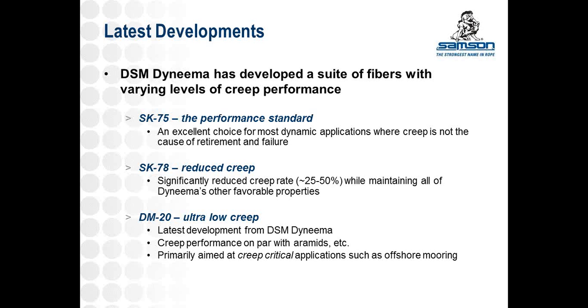Finally, DSM Dyneema has just released a brand new fiber, which they call DM20, which is their ultra-low creep fiber. Now this is a complete change. They actually went ahead and changed some of the chemistry in the fiber as well as the production process, and this has led to creep performance on par with fibers such as the aramids. So it is going to have a negligible amount of creep strain over its lifetime. That doesn't mean it won't have a creep failure. It will. It'll last much, much longer than SK75 or SK78, and it won't be stretching in that time. But like I said, it will happen to everything. So far, this fiber is brand new. It's primarily being aimed right now at creep critical applications such as offshore mooring. So we don't anticipate at this point to start selling Amsteel Blue made of DM20 quite yet. But we are investigating markets for that fiber.